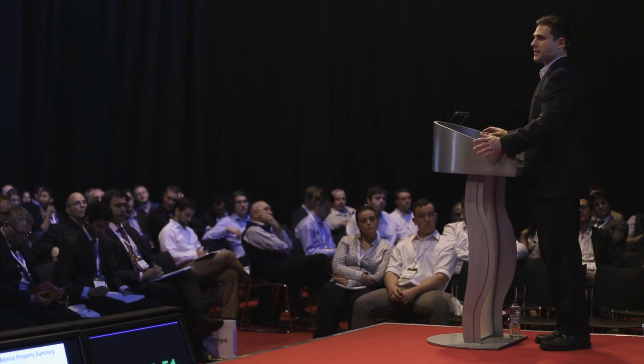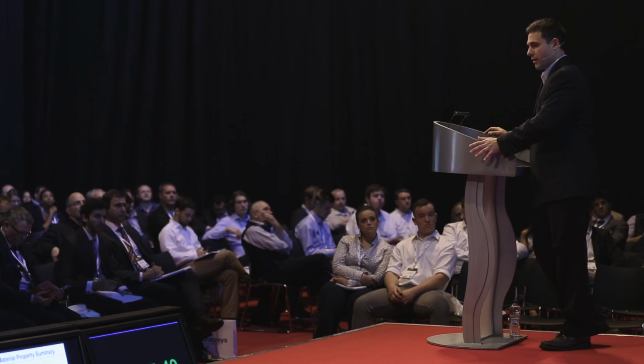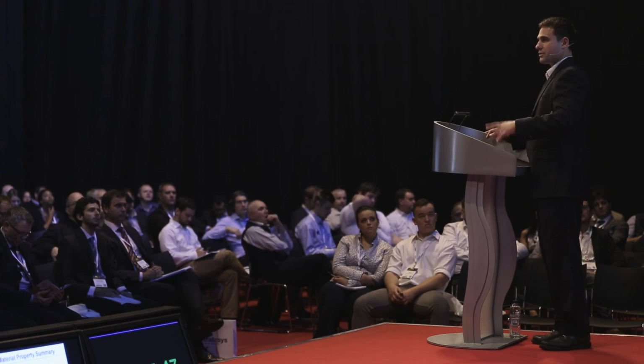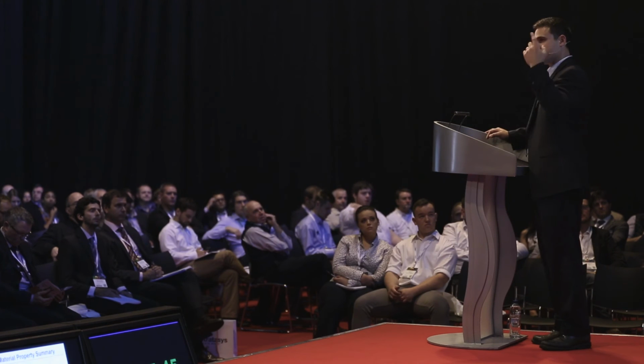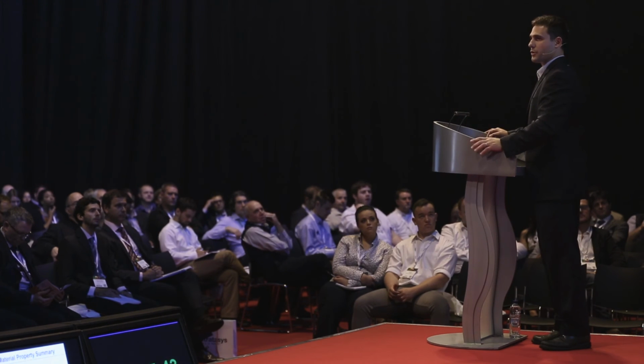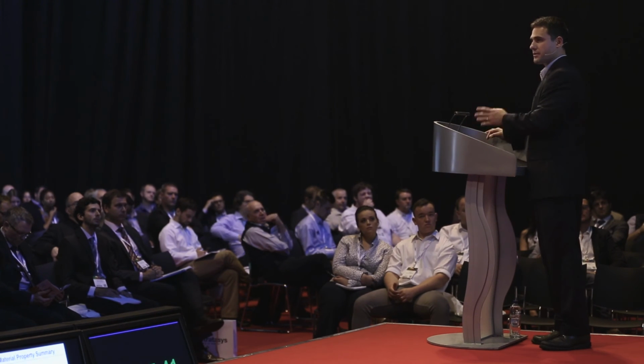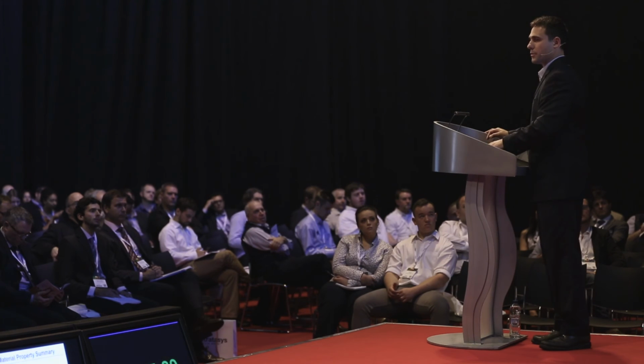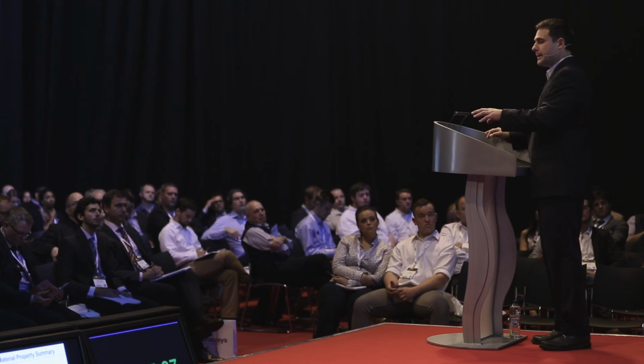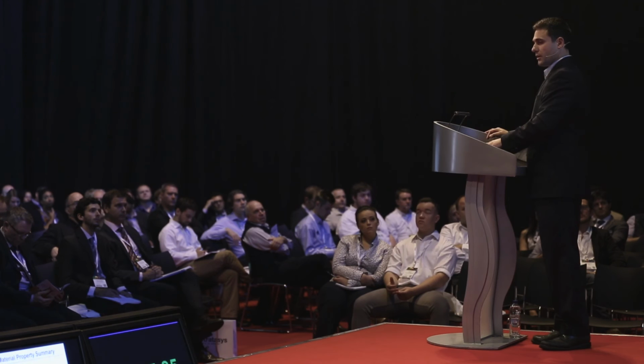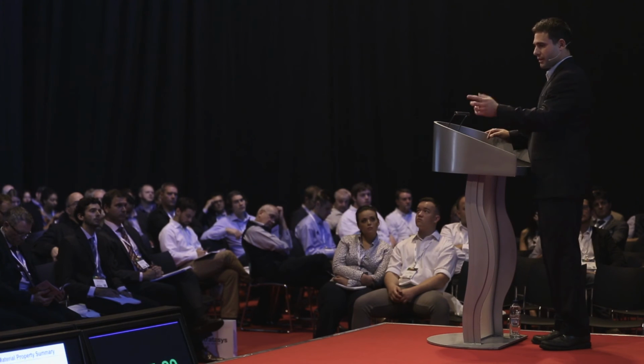So you're getting about a 3x increase in modulus in the polyaryl with a Tg which is almost 3 times higher, right? So now you start thinking about the application space that opens up, where you've got 3 times higher modulus and 3 times greater approximate temperature capability. That gives you quite a bit more room to move. And then with a nylon, you're basically functionally doubling your modulus, and you get a lot more temperature capability if you look at heat deflection data, which isn't here.